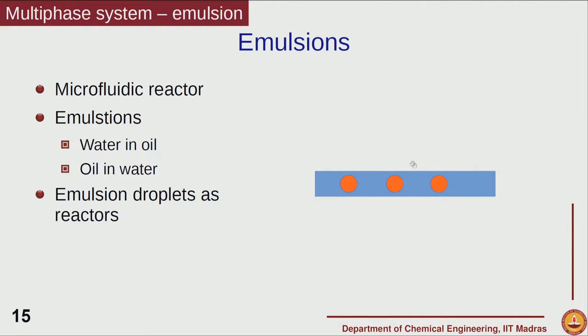For example, you could have the water phase as the continuous phase, and there is a monomer, initiator, and cross-linker which are in the oil phase. These can then start reacting, and once the reaction is over, the final particle you get — let's say of a polymer — will exactly be the shape of the drop itself. Since all the drops are the same, the overall particle size will also be exactly the same. In these cases the flow behavior of the emulsion systems is of importance, as it determines how the droplets will flow and what shapes they will acquire.